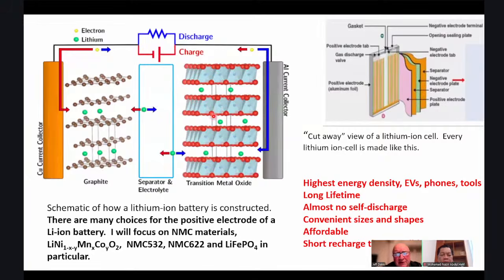And when the lithium-ion battery is charged, lithium atoms from the transition metal oxide dissociate into ions that move through the electrolyte and electrons that move through the external circuit. And the lithium atoms end up in between the graphite layers. And the reverse happens on discharge. The lithium atoms that are within the graphite travel as ions and electrons back to the transition metal electrode.